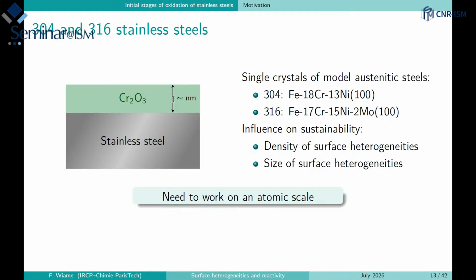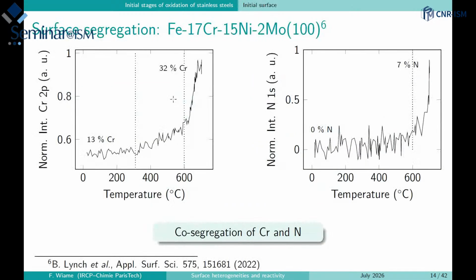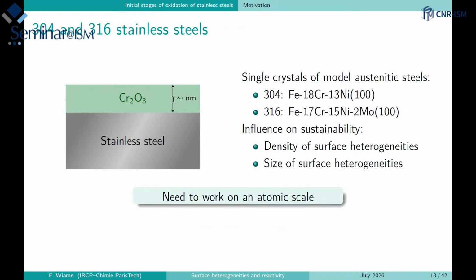And so we are working with some model crystals, so single crystals of this model austenitic steel of 304 and 316, which are very widely used stainless steels, with samples which are in fact single crystals of iron, chromium, nickel, and iron, chromium, nickel, molybdenum for the two 304 and 316 alloys, single crystals oriented with the 100 direction. This is an FCC structure in this concentration.